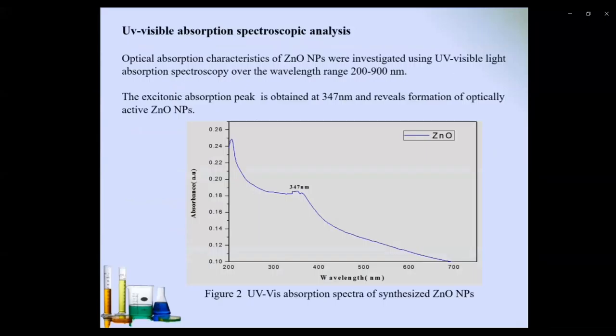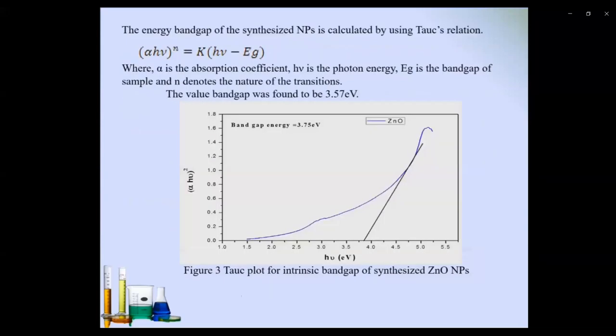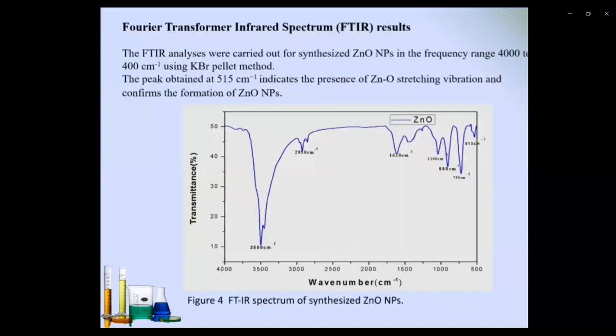From UV visible absorption spectra, you can observe here that the synthesized nanoparticle exhibits an excitonic absorption peak at 347 nanometer and reveals that it is an optically active nanoparticle. And further, the energy band gap of synthesized nanoparticle is calculated by using the Tauc relationship, which is given by alpha h nu raised to n is equal to k into h nu minus Eg. Therefore, the graph is plotted with respect to the above relationship.